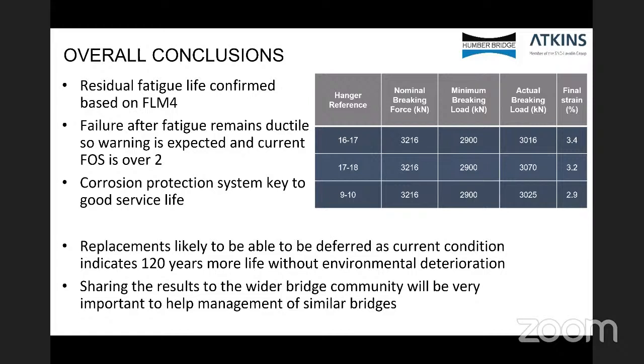And what we would quite like to do is share these results with other long span bridge owners so that it really promotes low intervention structural refurbishment. In this instance, we could have gone down the line of replacing all the hangers. We've certainly developed a methodology to do that. However, although expensive, this testing has confirmed that there's significant residual life in the hangers, and deferring the replacement by 10, 15, 20 years, depending on the effectiveness of the corrosion protection system, will have a significant whole life cost benefit to the bridge at the moment.